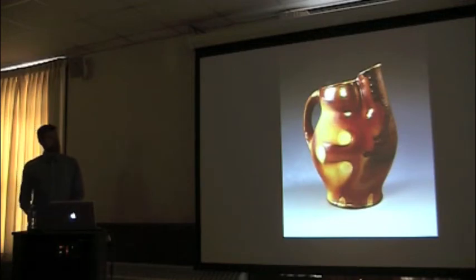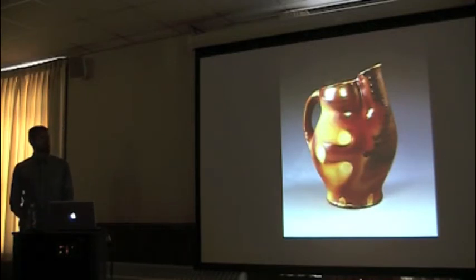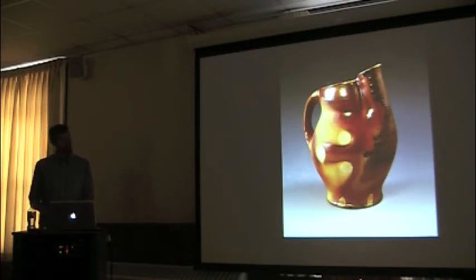Think about a campfire — you have all those little sparks flying in the air. In ceramics we call that fly ash. That ash flies through the kiln and sticks to the pots, the walls, the shelves — it's actually the same thing that builds up in your chimney as creosote. But because we're going to such high temperatures, it melts into a natural glaze. On the front of this pitcher, those dark brown drips are actually ash — a natural glaze. To keep pieces from sticking to the shelf, we use wadding, a refractory substance rolled into little gumball-sized shapes that you stick to the pot. Those three dots on the pitcher are wadding; the pitcher was fired on its side. I try to use that mark to my advantage — as a decorating technique on the side rather than three dots on the bottom.